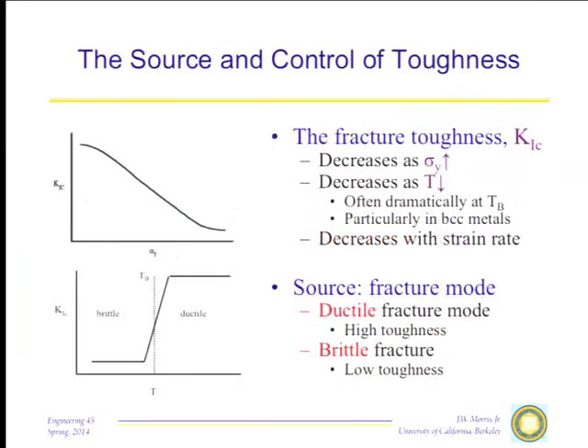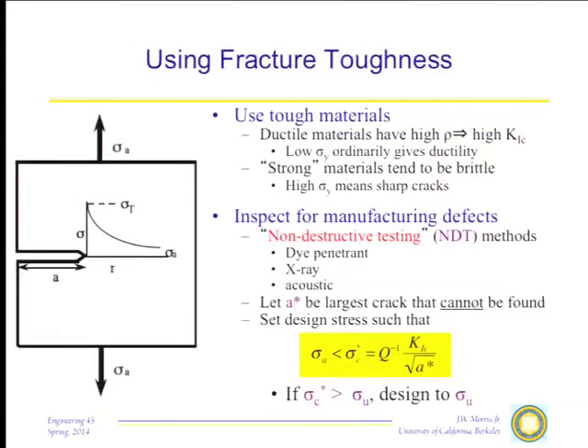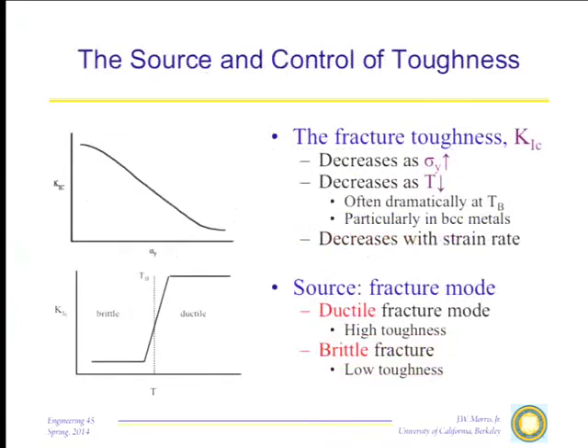Well, if you're going to use this kind of fracture toughness design, it's critically important that you use the best materials you can possibly use, the best toughness you can possibly use. So the thing we've got to work on next is what determines the toughness of a material. And that gets us back into the other problem that they ran into over here in Richmond in the Second World War, and that's the ductile-brittle transition. It turns out that there are really two things that govern the fracture toughness. One is the yield strength.